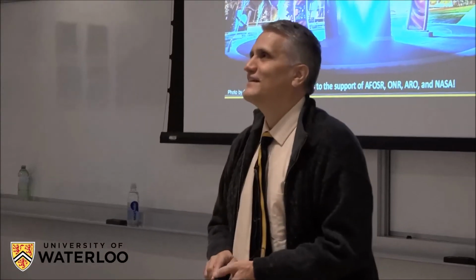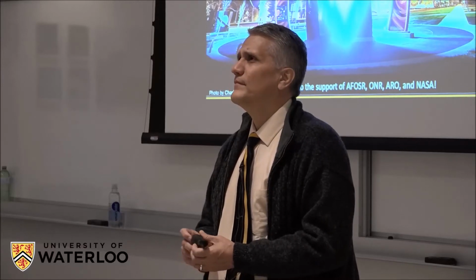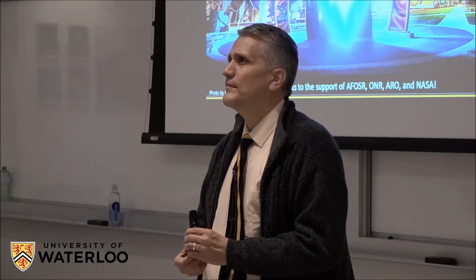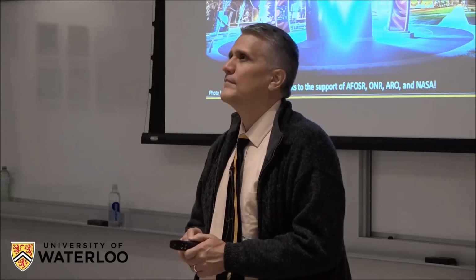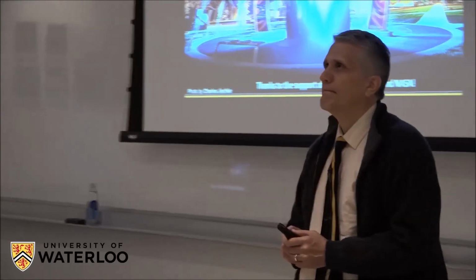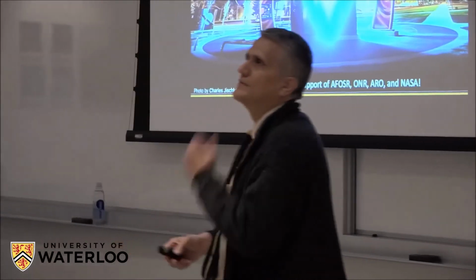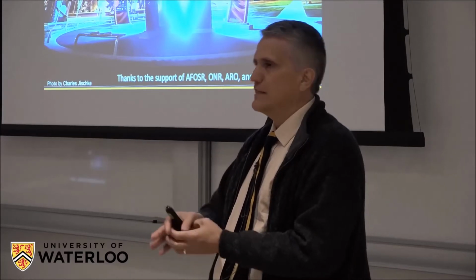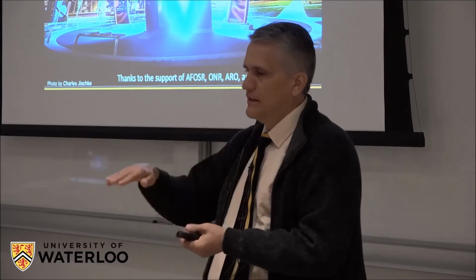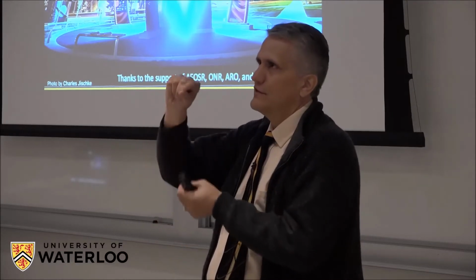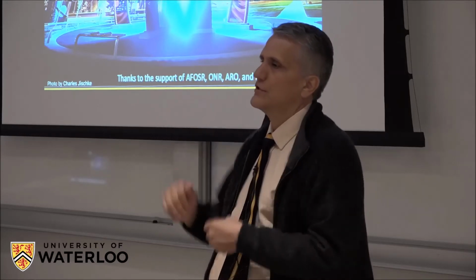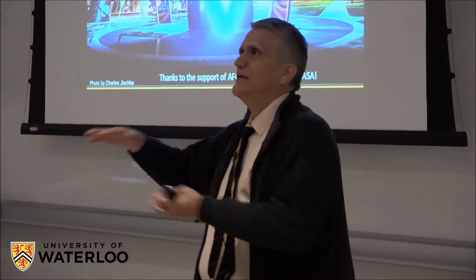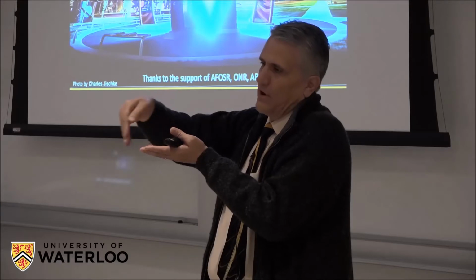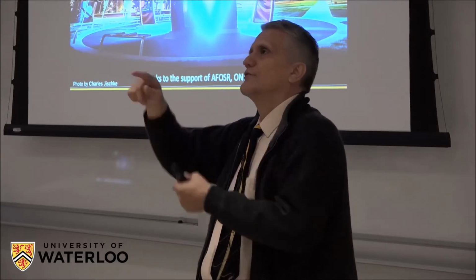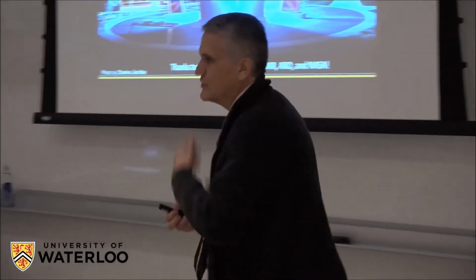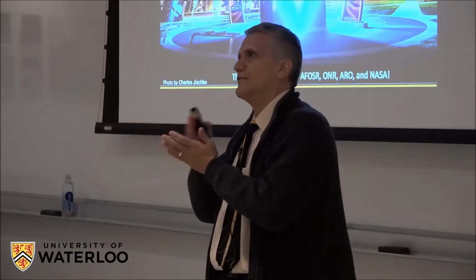With regards to the introduction of the microstructures to change the combustion behavior, was there any optimal equation between the space allowed between the layers, or anything related to what particles you're using? The general answer is yeah, it makes a big difference. I'll give an example with the nanofoils. That's not material that we make. As those are deposited, as you go thinner and thinner with the inner layer spacing, the propagation speed goes faster and faster. But you get to a point where, even as you deposit the layers, a little bit of partial reaction occurs and it starts to slow down, and you have partially reacted material. So there's often an optimization of the layer thickness and so forth.